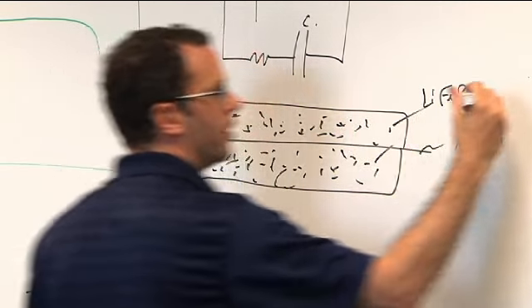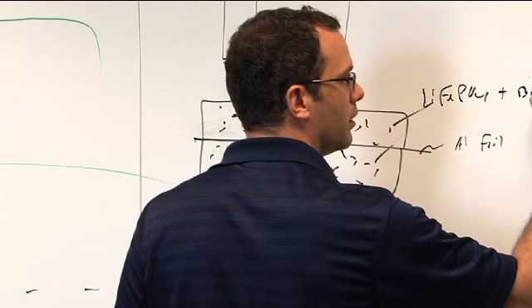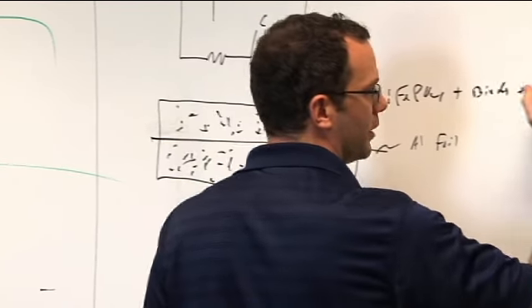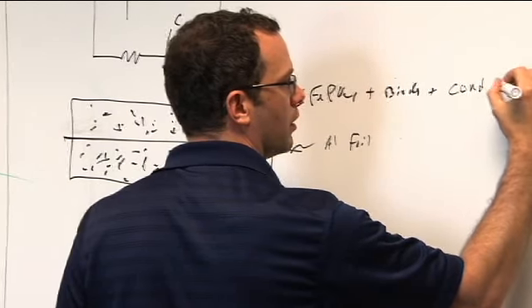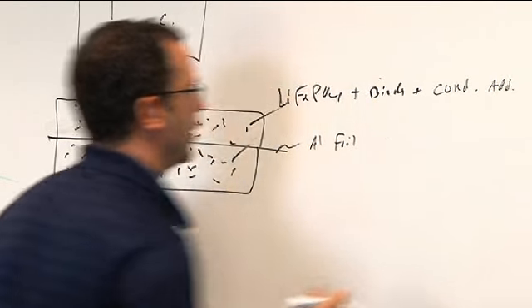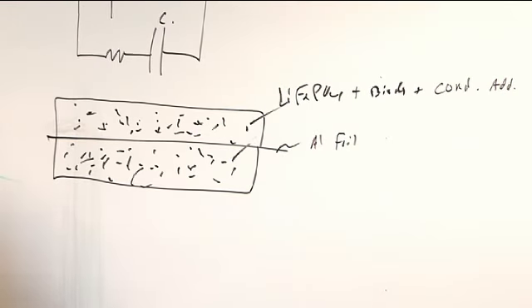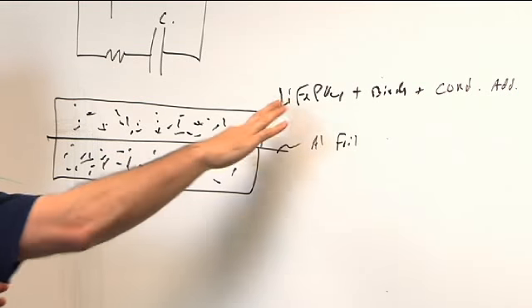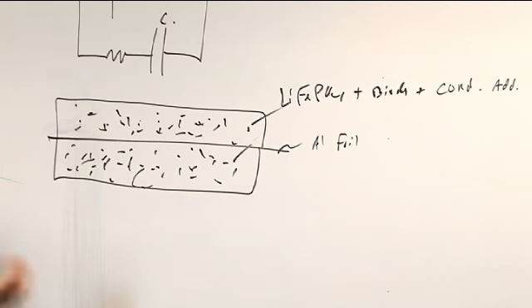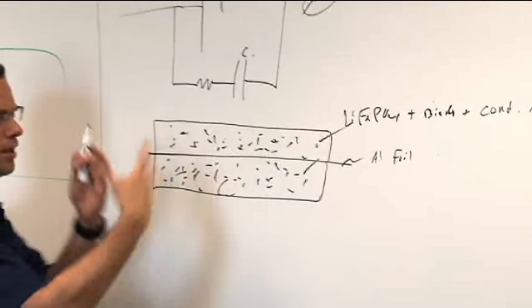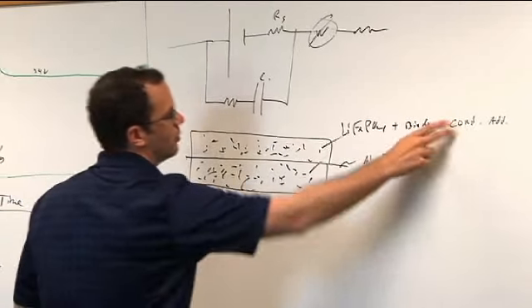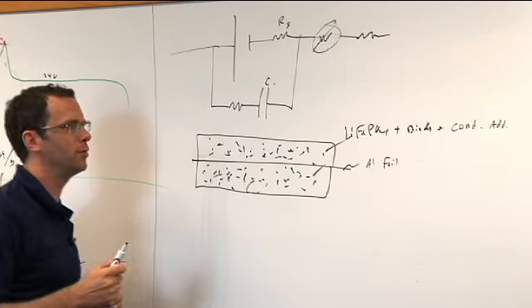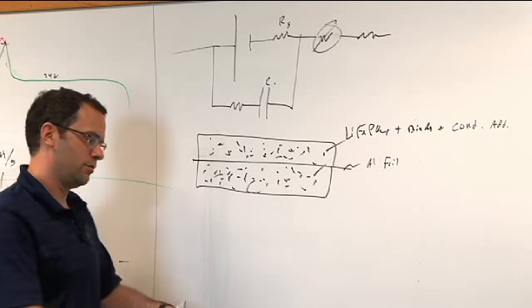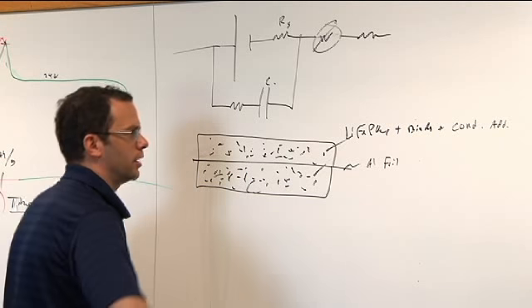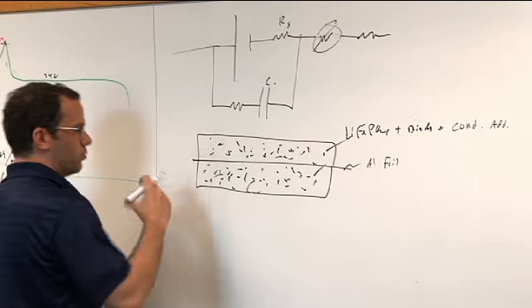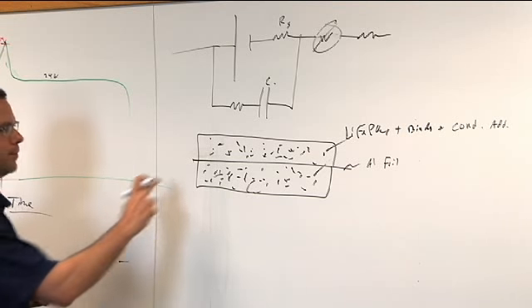And this is lithium iron phosphate plus a binder plus a conductive additive. Right, and it's made typically by either a spray coating or a slurry casting. You mix these nanoparticulate powders, lithium iron phosphate, with like some carbon black to help get good electronic conductivity, and a small amount of a binder, which is usually PVDF, polyvinylidene difluoride, and it's sort of a slurry, and you can spray it and dry it, or you can blade cast it and dry it. And it's a roll-to-roll process that's done in bulk in battery factories.